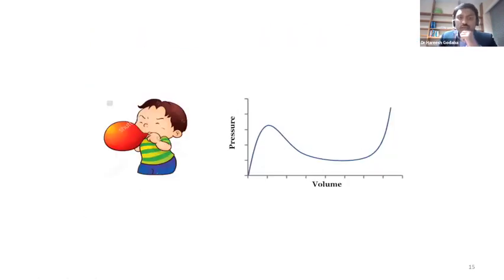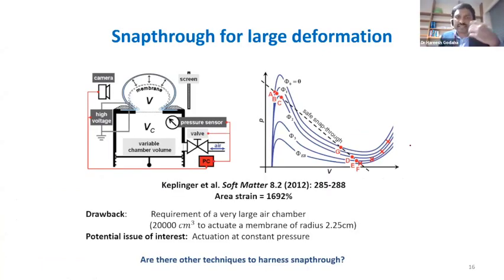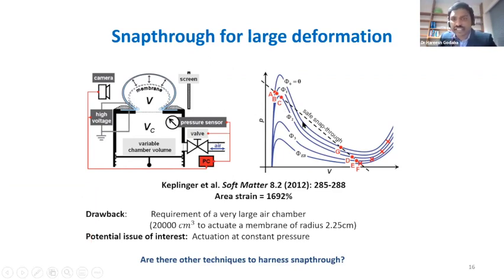Now, on the other hand, instead of inflating by increasing the volume, if you connect the balloon to a pressure regulator and you slowly begin to increase the pressure, what you will see is that once the pressure reaches this point and you slightly increase it, there is no stable state close to this. So the membrane basically jumps to this very large volume state, and this is called a snap-through expansion of the balloon. Some researchers found that if we use this snap-through expansion and control the pressure volume loading curve, we can achieve a safe snap-through.